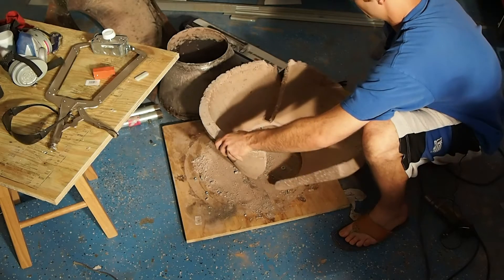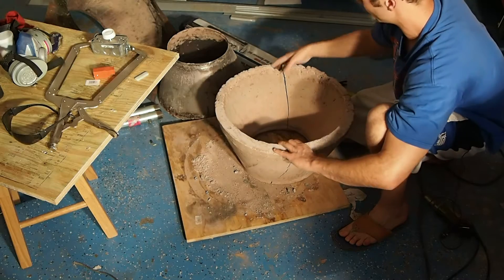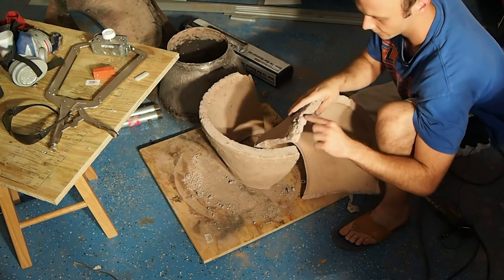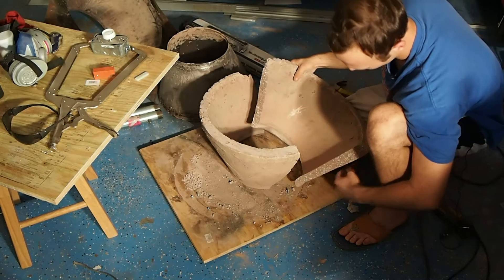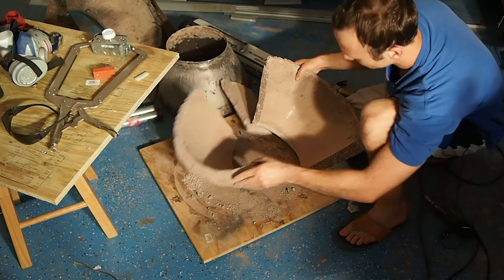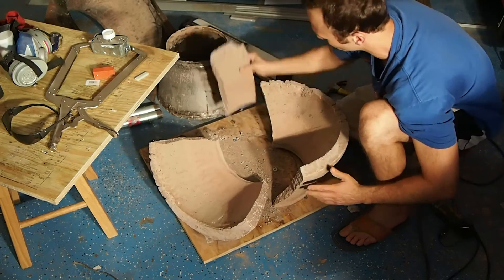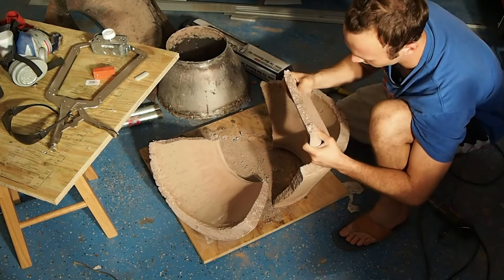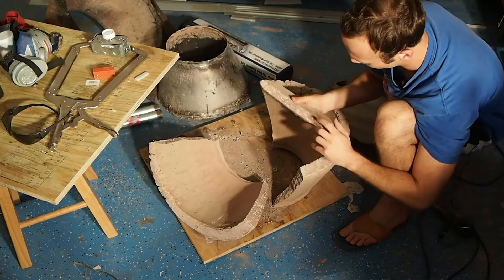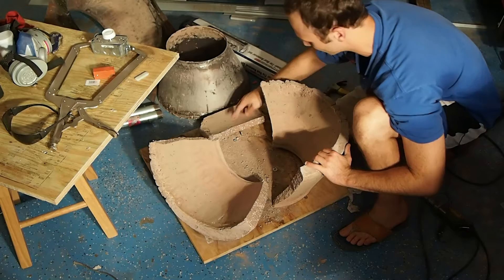This is basically what it looked like when it was together. This side did not fill very well — as you can see, there are a lot of craters and different pits and pockets. Looks like I used a little too much perlite in the mix and made it pretty weak. You can see how it's just falling apart, so it's pretty brittle. That's kind of the fear when I take out the Portland cement — how much more brittle it'll be. But this is basically a product of too much perlite and it not being packed in enough.